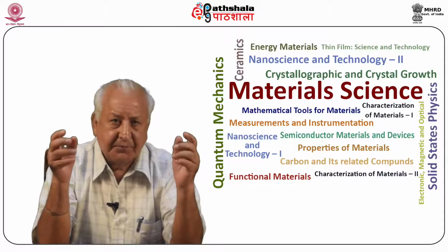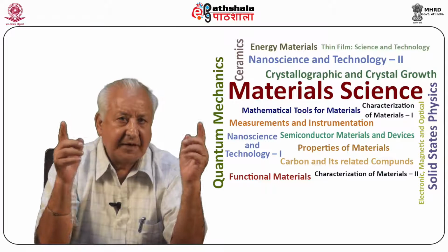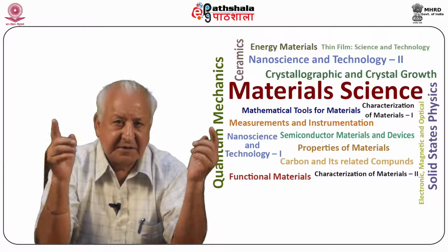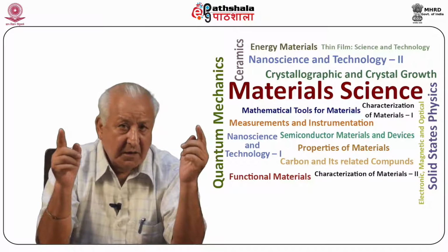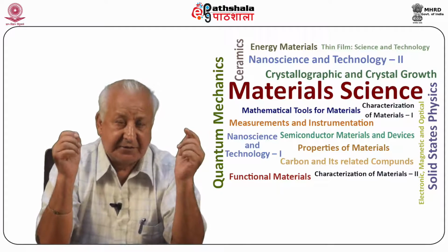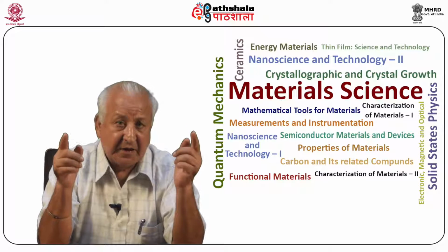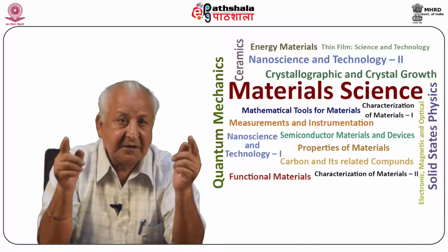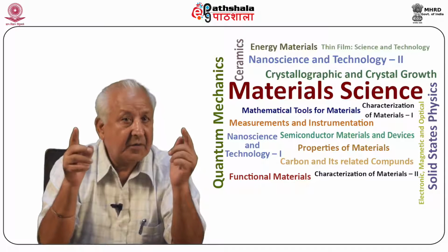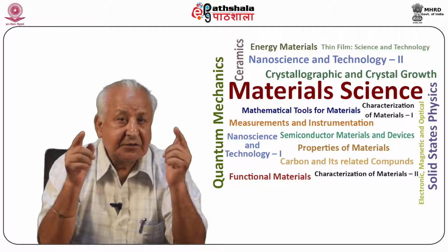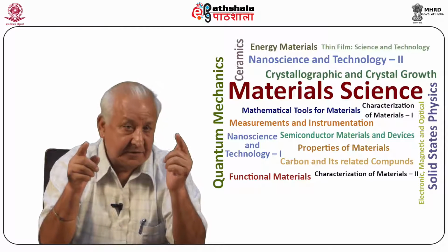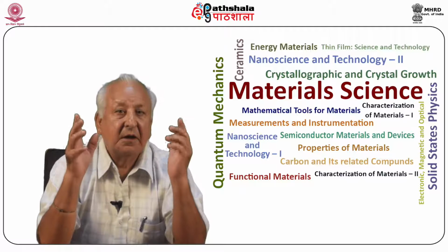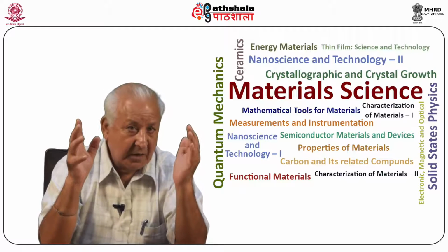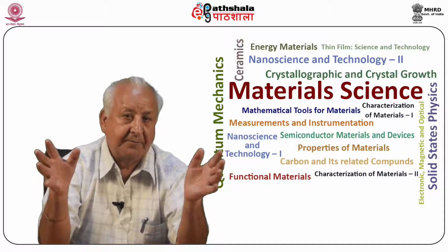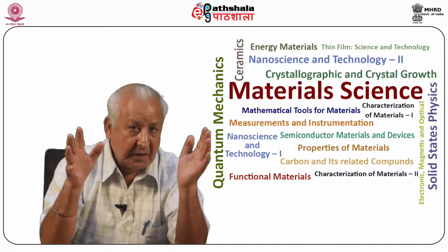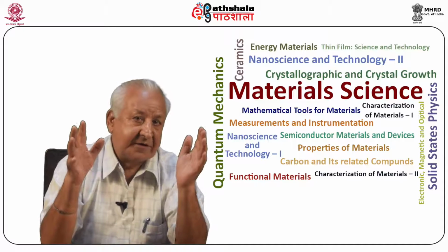Coloring of crystals can be achieved in different ways, as described. Number one, by addition of suitable impurities like transition element ions with excited energy levels. Number two, by adding a stoichiometric excess of cations by heating the crystal in the alkali metal vapor, followed by quick cooling. The color of the crystal would depend on its nature.